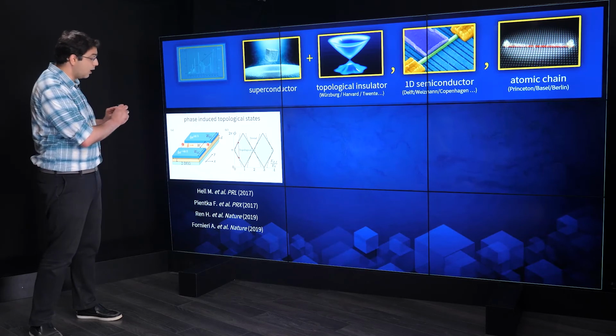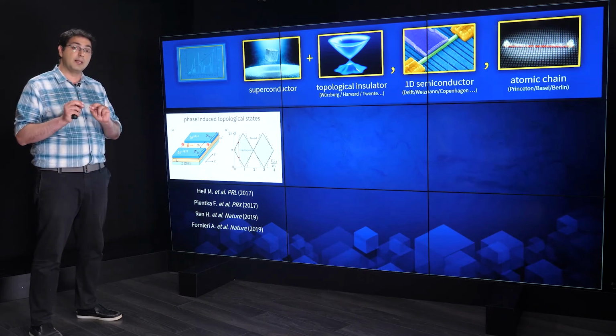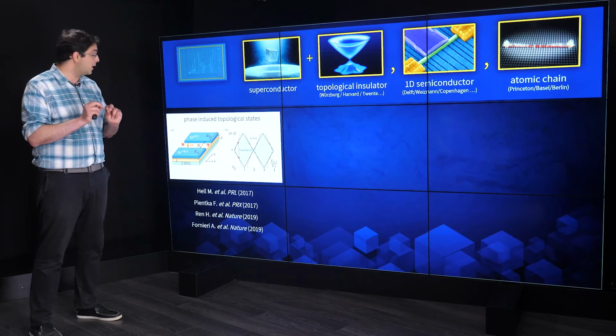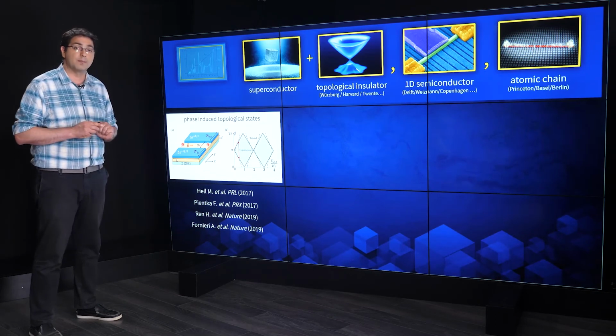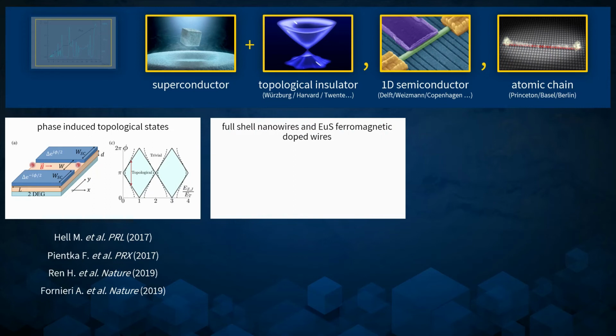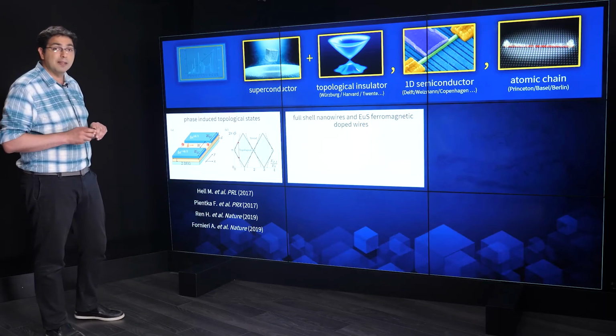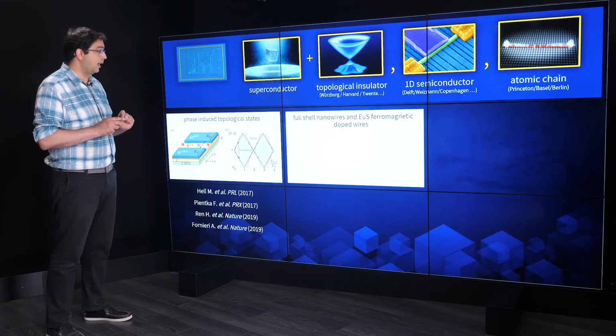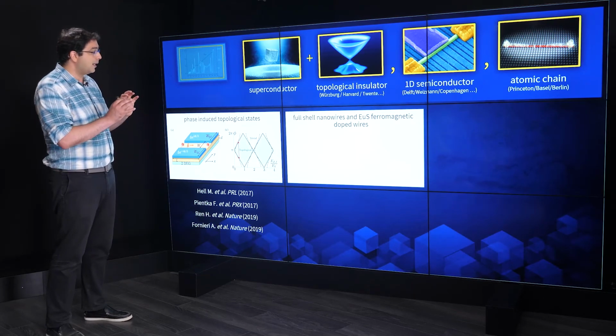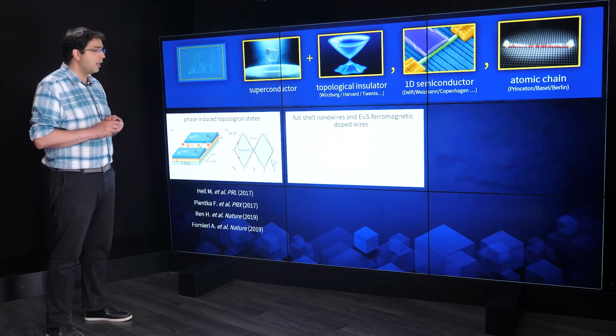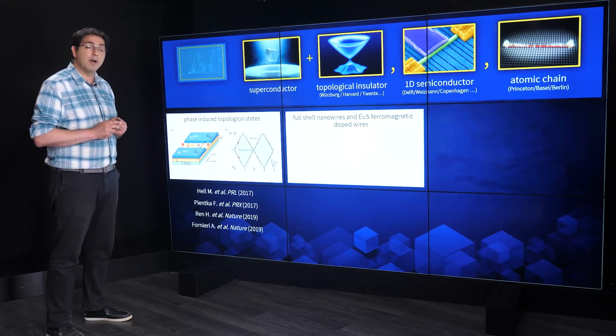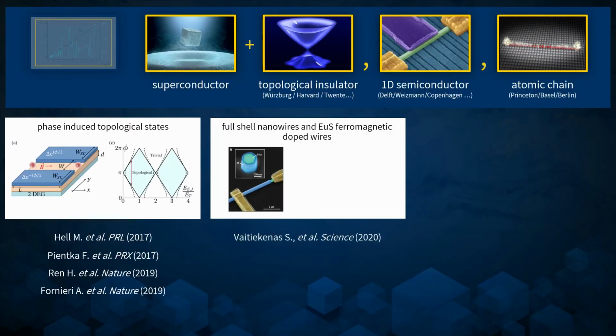So they were also able to look at zero bias peaks, which are evidence for Majorana zero modes, in these two systems. Now a second platform is also a continuation of the nanowires that I mentioned before. Here this is mainly led by Copenhagen and Microsoft, which is basically using full-shell nanowires and europium sulfide ferromagnetic doped wires. So here you can see, for example, the indium arsenide nanowire that I showed you before in green, and it has a shell of aluminum.